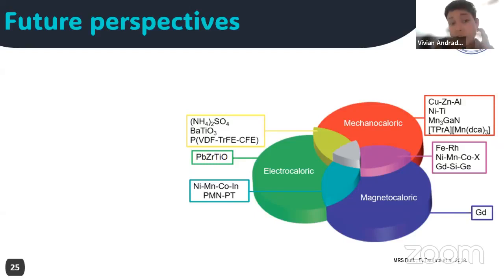Are there in this case cutting-edge materials without gadolinium, for example? Yes, there's a lot of prototypes using lanthanum iron silicon, because lanthanum is actually a reject when you mine the element from the earth. The lanthanum is usually the rejection thing. So I already tried to put lanthanum at gadolinium silicon germanium, and it breaks everything, reduces the temperature. It's not good to use lanthanum in the case of gadolinium silicon germanium, but in the case of lanthanum iron silicon, it's really good.